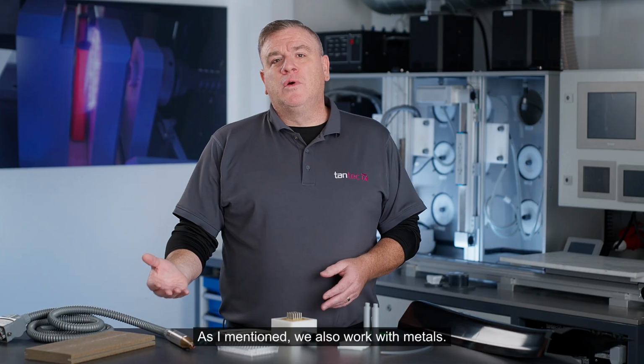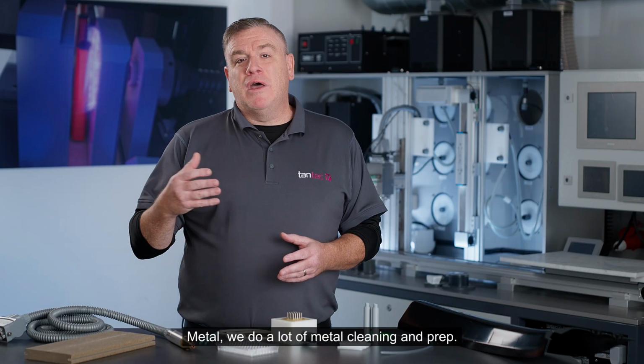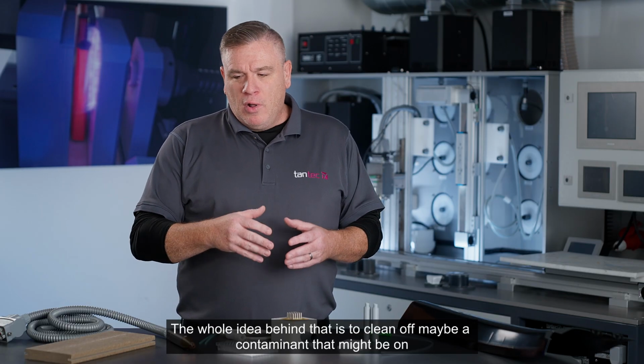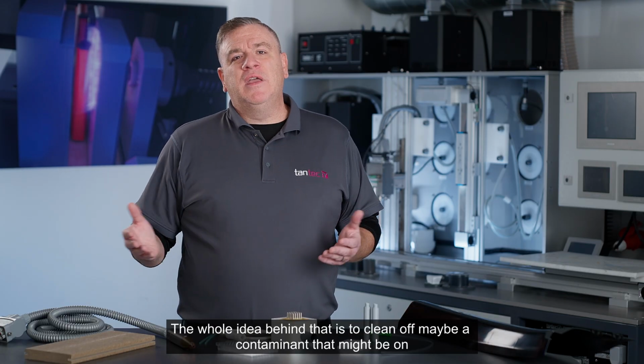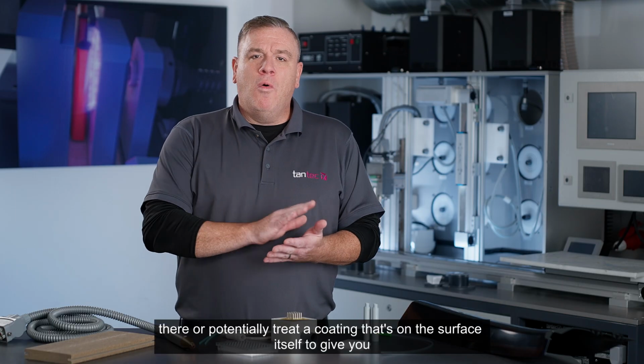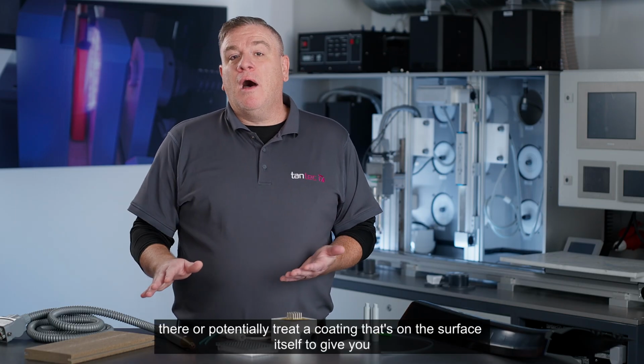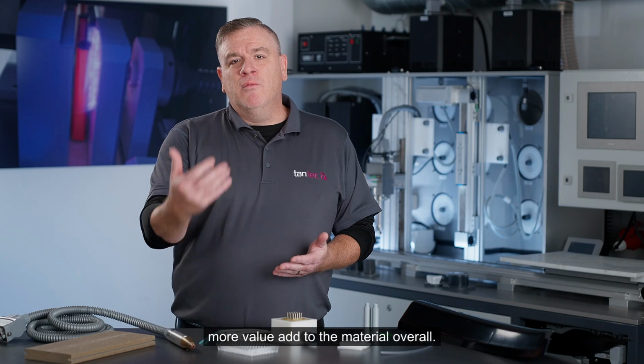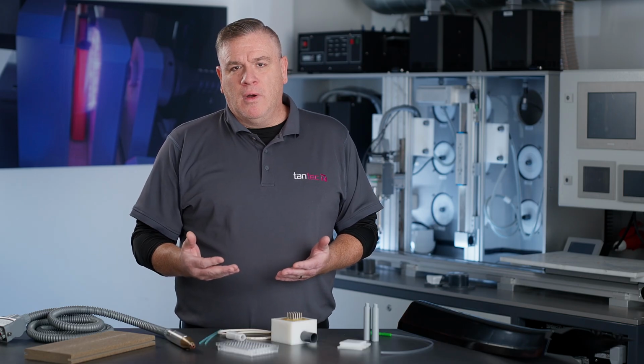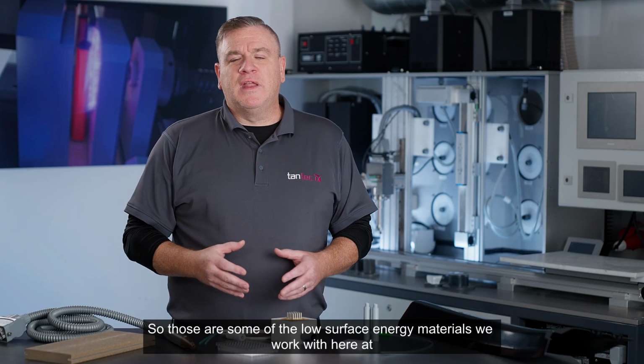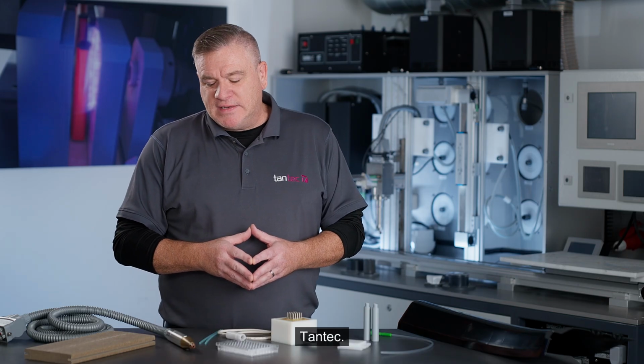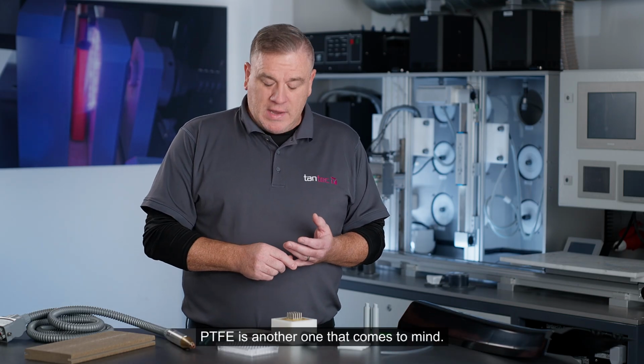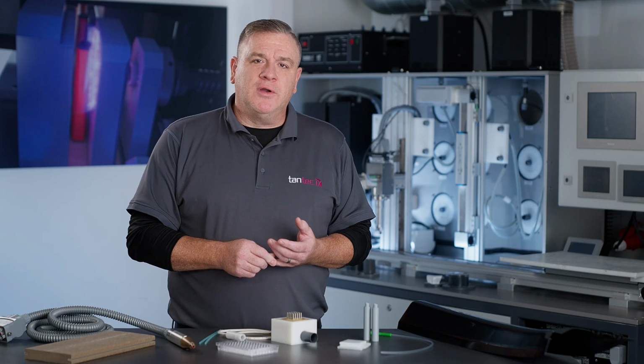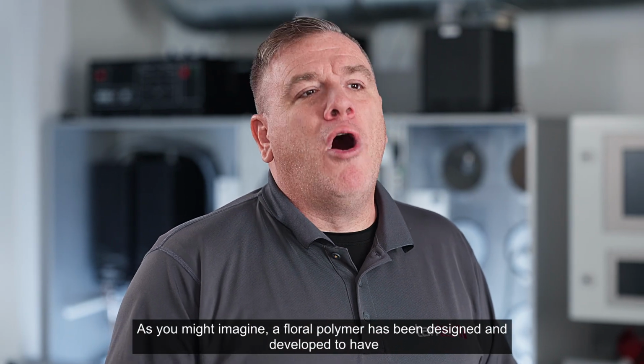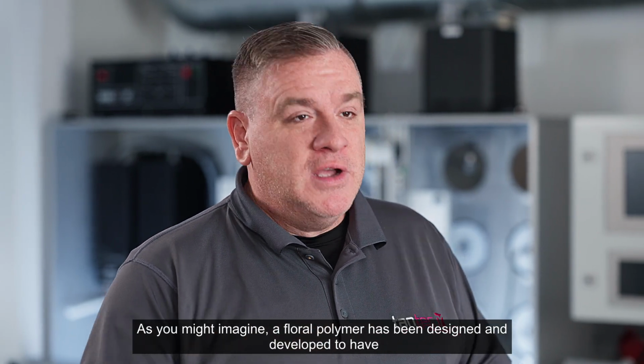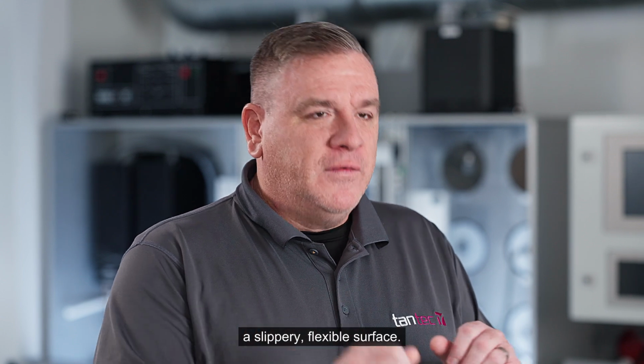As I mentioned, we also work with metals. Metal, we do a lot of metal cleaning and prep. The whole idea behind that is to clean off maybe a contaminant that might be on there, or potentially treat a coating that's on the surface itself to give you more value add to the material overall. So those are some of the low surface energy materials we work with here at Tantec. PTFE is another one that comes to mind. That's a really challenging material. As you might imagine, a fluoropolymer has been designed and developed to have a slippery, flexible surface.